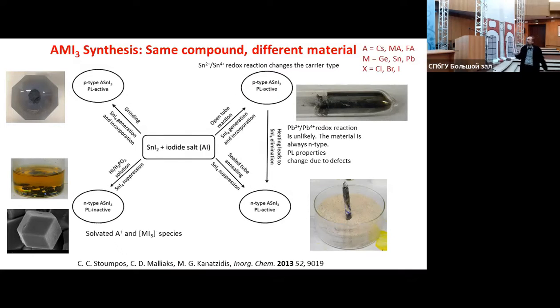What's so special about perovskite? Perovskite have a very special property, which to me was eye-opening when I started looking into this material. Basically, that you can synthesize the same compound with a different method and produce a material with different properties. And using this simple reaction, I synthesize tin iodides, I react it with an iodide salt, and you make the perovskite. It is as simple as that. You can do it mechanically, simply by grinding. You can melt it to form ingots, and you can also grow these crystals from solution. Each and every method gives different properties.